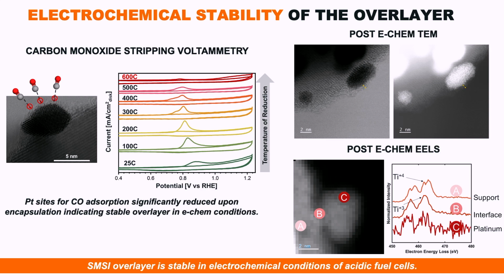Then we performed some accelerated stress tests, or basically we cycled the catalyst in EChem conditions, and we looked at the catalyst post EChem using TEM and EEL spectroscopy, and we could still observe the overlayer post electrochemistry. And through EEL spectroscopy, we could look at the titanium edge as we went from the support to the interface to the platinum, suggesting that the overlayer is still intact even after long-term cycling tests.